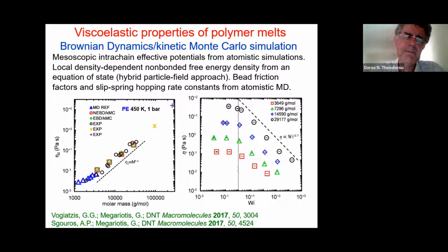So in this sense, we have a hybrid particle field approach because the intramolecular contributions are represented in a particle sense as interactions between particles. The non-bonded contributions are represented in terms of a density field. And of course, this density is shaped by where the beads are. In addition, we need a friction coefficient to describe the dynamics in the Brownian dynamics, and that we extract from molecular dynamic simulations of oligomers. And also we need slip spring hopping rates. These are related to the bead friction factors. So we can parameterize this mesoscopic model essentially with no adjustable parameters based on the atomistic simulations of small molecular weight analogs.